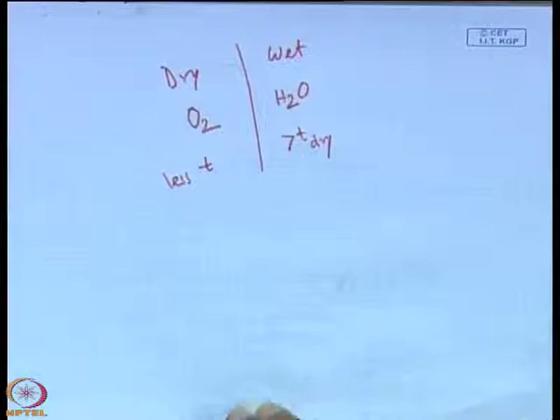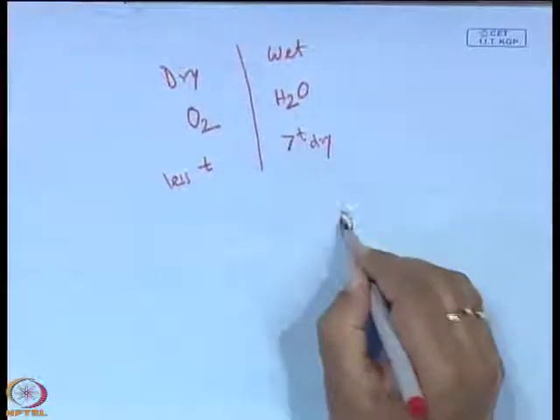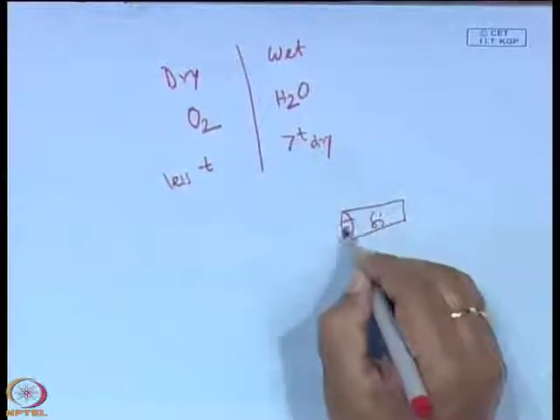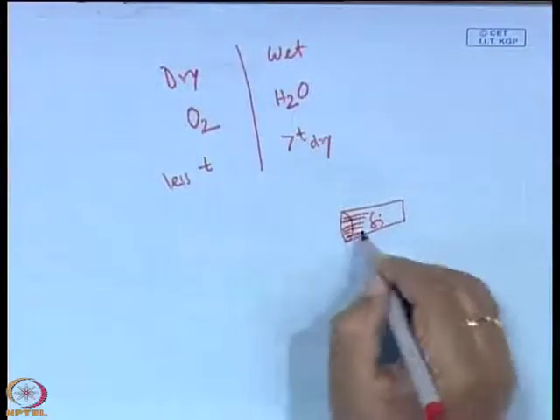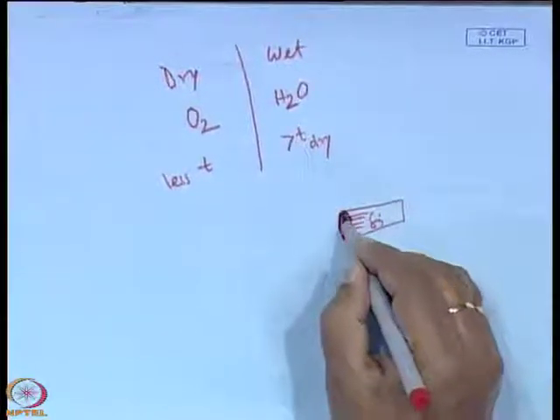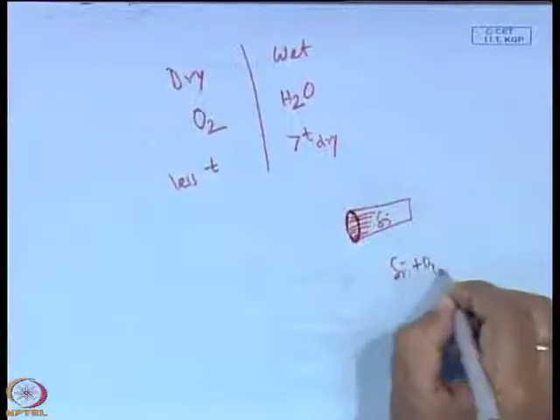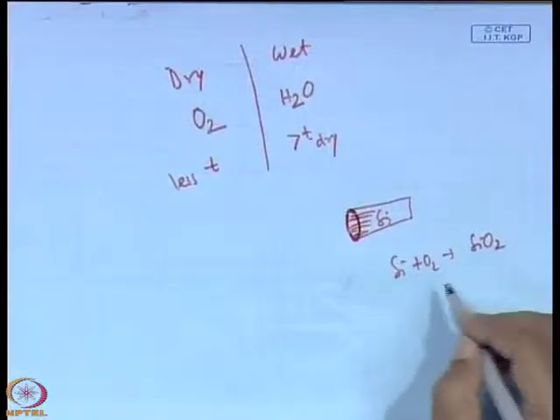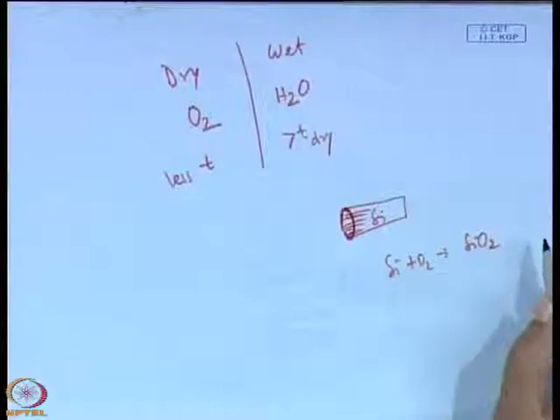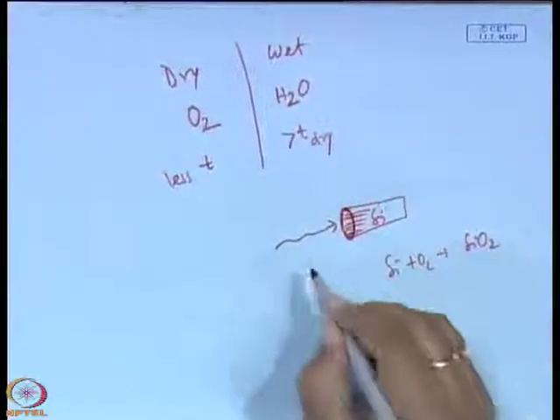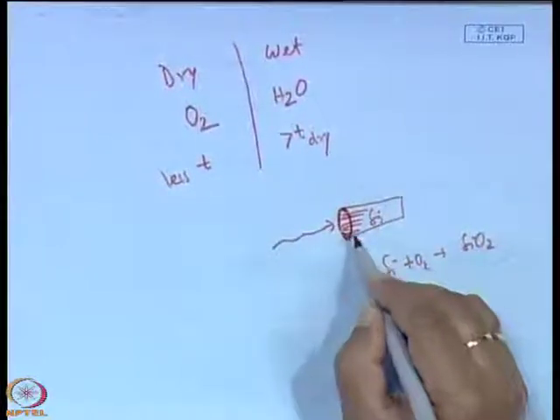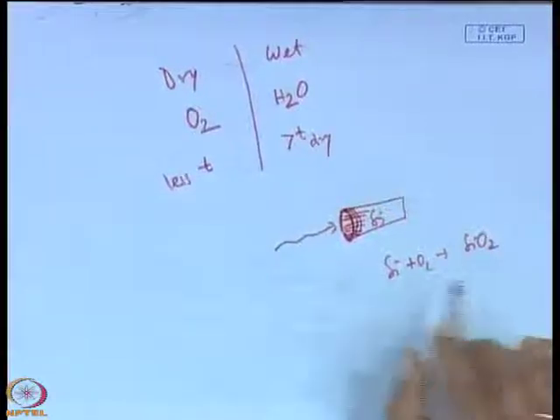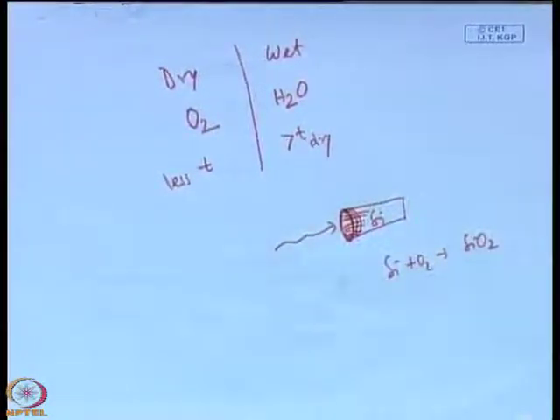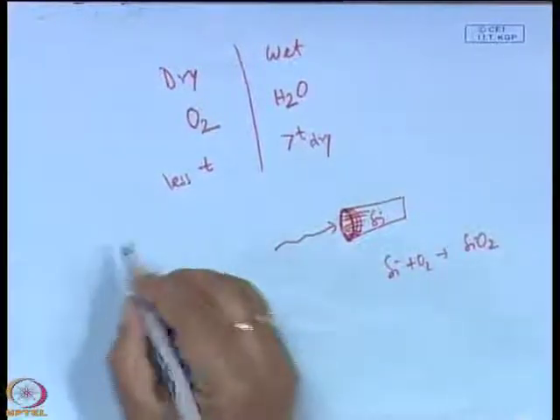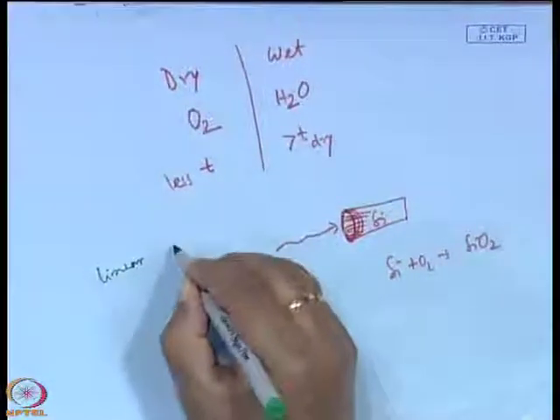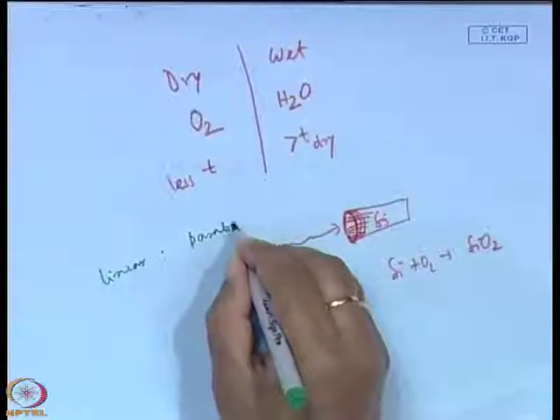And also we have seen the kinetics of growth: first a layer of SiO2 is formed on the silicon. The first rate limiting factor is the reaction of the Si with oxygen to form the SiO2, which is linear in nature, and the rate constant depends on it linearly. Then the oxidizing species diffuses through the SiO2 layer to reach the surface for the reaction. So, it can be the parabolic rate constant. Depending on those models, the linear rate constant is different from the parabolic rate constant after the initial oxidation.